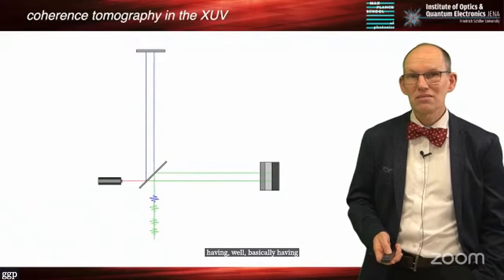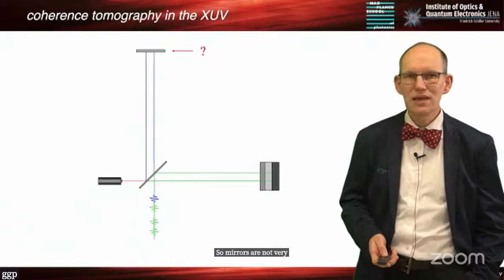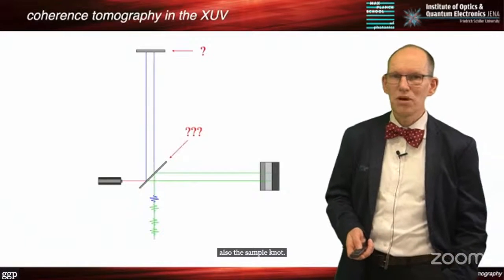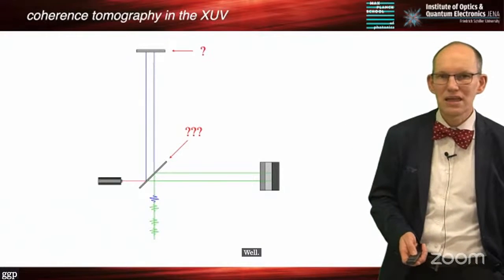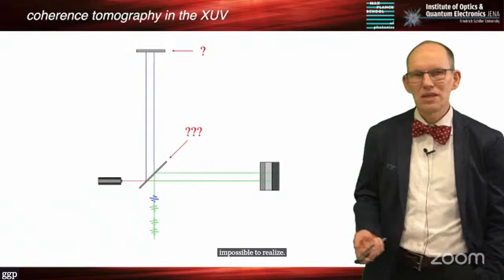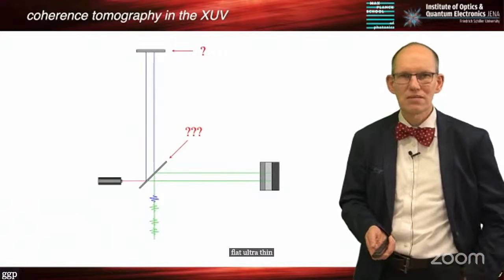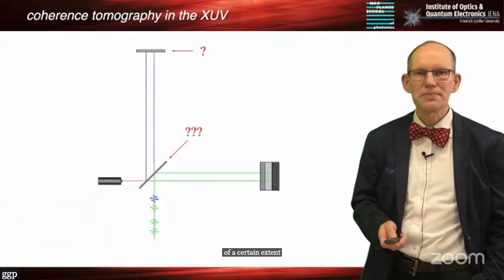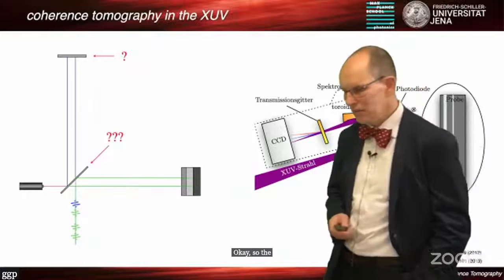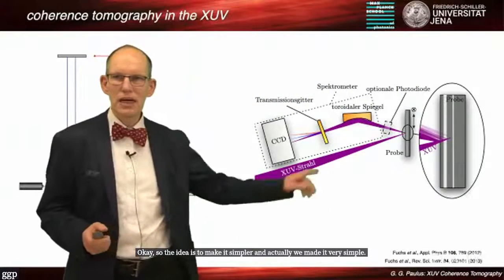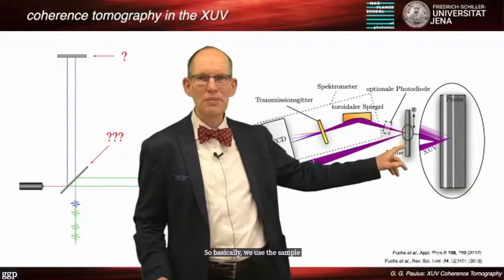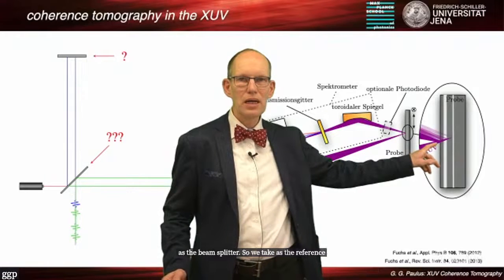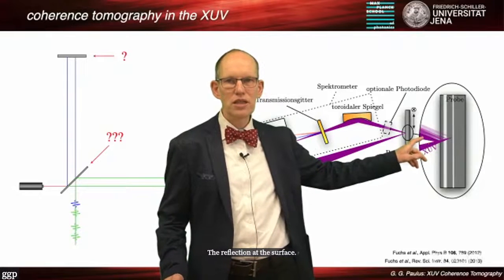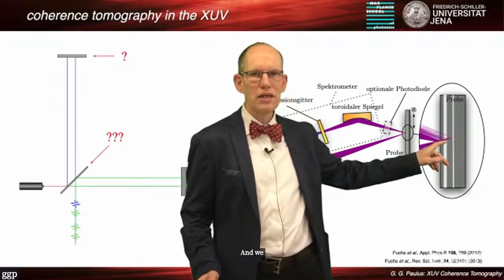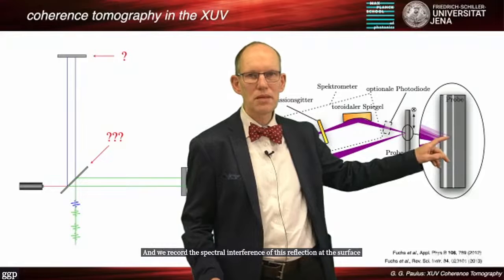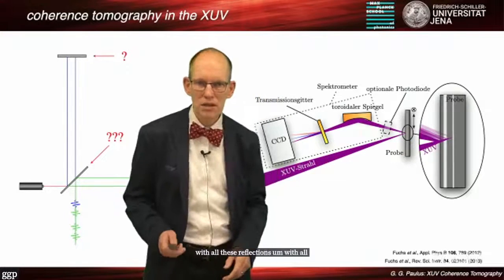Basically we have no mirrors. Mirrors are not very highly reflective in the XUV, and the sample also not. Even more difficult are beam splitters. They are practically impossible to realize, because you would need a flat, ultra-thin surface of a certain extent. So that's difficult, at least. So the idea is to make it simpler, and actually we made it very simple. We use the sample as the beam splitter. We take as the reference beam the reflection at the surface, and we record the spectral interference of this reflection at the surface with all the internal reflections.